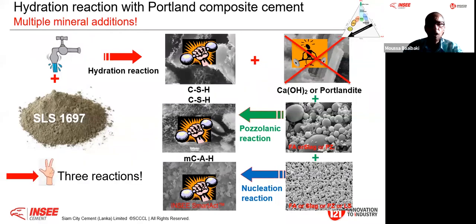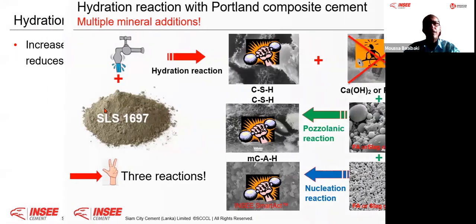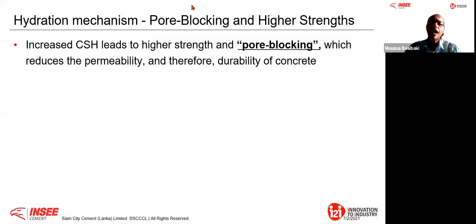And in this case, we now have three reactions. This is a triple reaction. Therefore, you see, we are fully taking advantage when I talk about calcium silicate hydrate plus the activation system, where pH plays a big role. We are able to fully take advantage of this main constituent of the Portland composite cement. That is why, if you look in terms of hydration, what we call the hydration mechanism, this is what we call pore blocking, or what we say developing high strength.